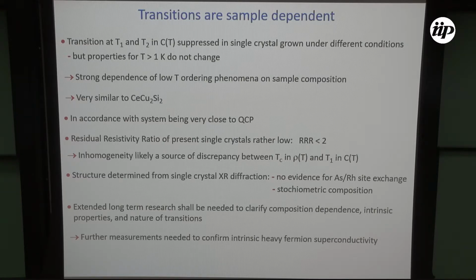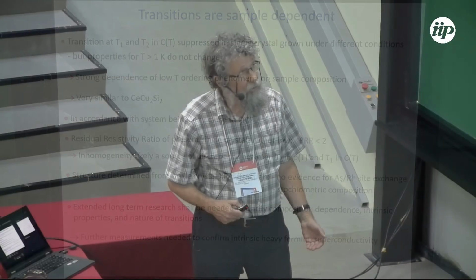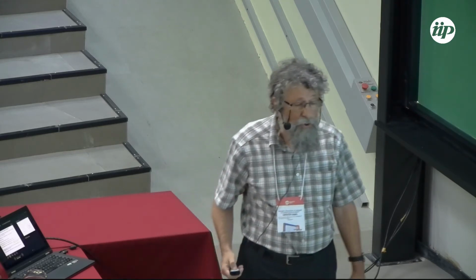But we also have to say that the residual resistivity ratio of the present crystals is rather low. We are just at the value of 2. And therefore, we suspect that inhomogeneity is likely a source of the discrepancy between the superconducting transition observed in the resistivity and T1 observed in the specific heat. It's normal, if you have a distribution, that the resistivity transition is well above the transition in the specific heat.